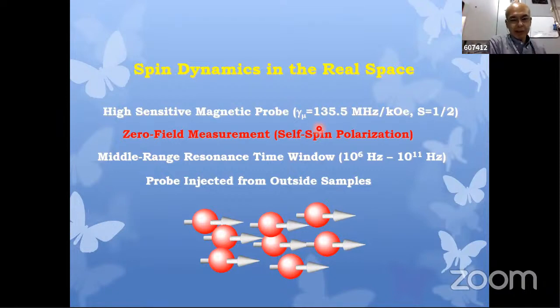The muon has a self-spin polarization. Self-spin polarization means that from the beginning of the creation of the muon, all the muons, surface muons, have the same spin direction automatically, even in the zero field condition. In nuclear magnetic resonance, what they are doing is applying a strong magnetic field to make this kind of spin polarization of the nuclear dipole. However, even if we don't apply any magnetic field to muons, the muon can show the self-spin polarization. That means MUSR can do any resonance experiment in the zero field condition. Zero field condition means quite ideal conditions for research in magnetic materials. So we can say the muon can give us ideal data taken in magnetic materials.